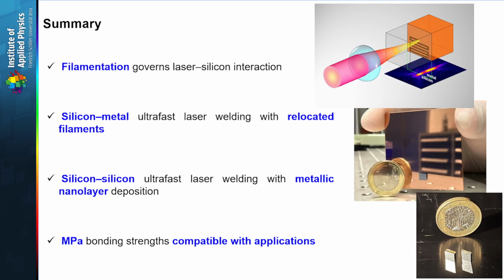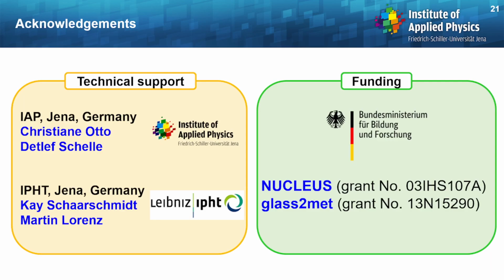So to summarize, we have seen that filamentation governs laser-silicon interaction in the POC. Also, silicon to metal ultrafast laser welding is possible when you relocate the filaments and you take into account the nonlinear focal shift. By adding a step of metallic nanolayer deposition, it is possible to even transfer this to silicon to silicon configurations. And moreover, in both cases, we reach megapascal bonding strength, which is compatible with applications.